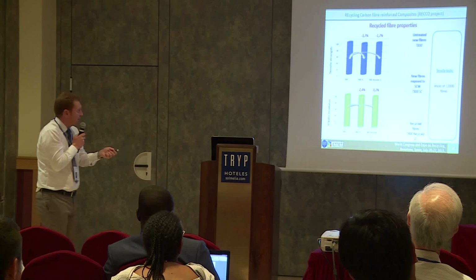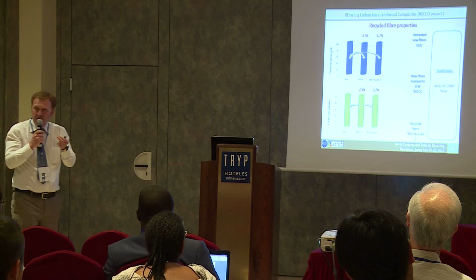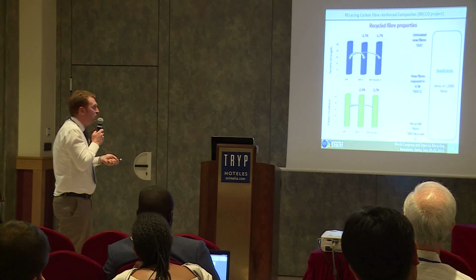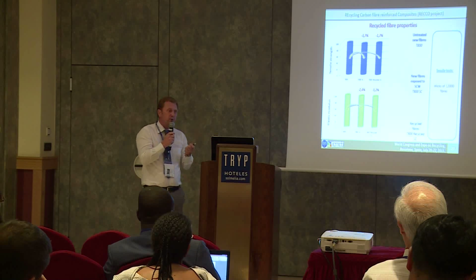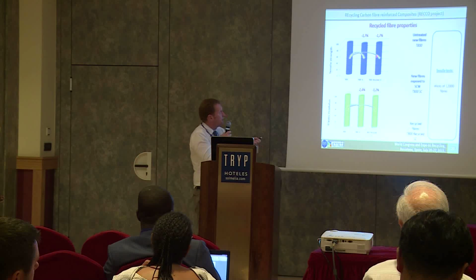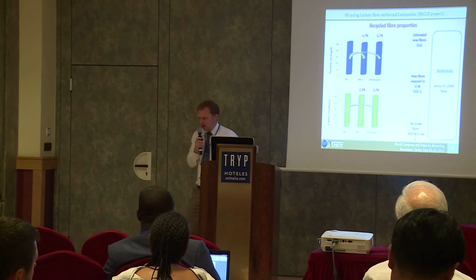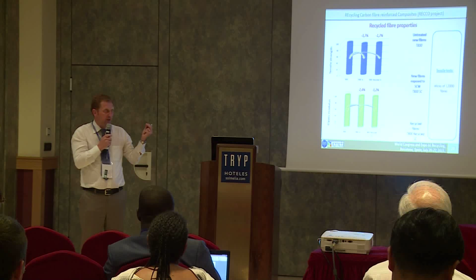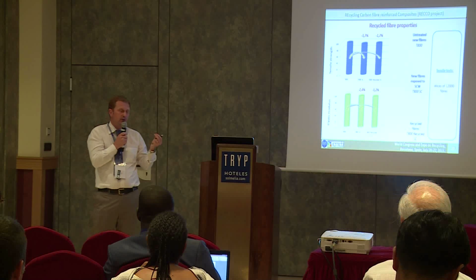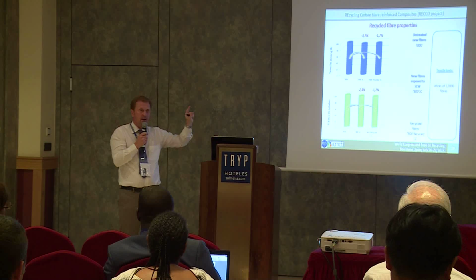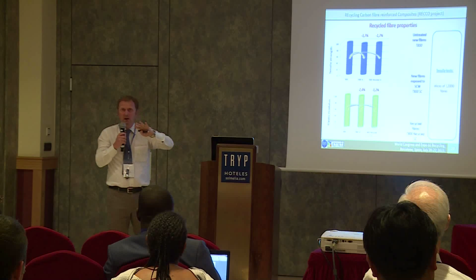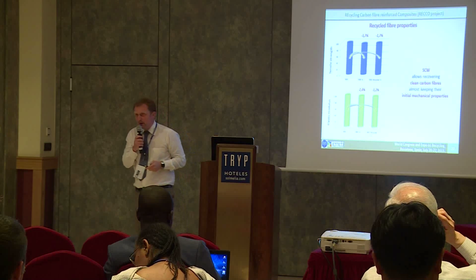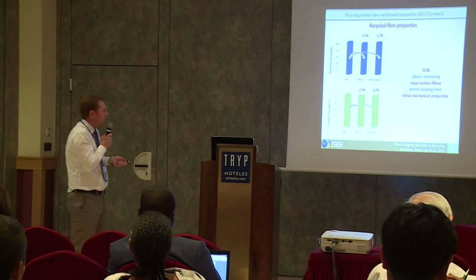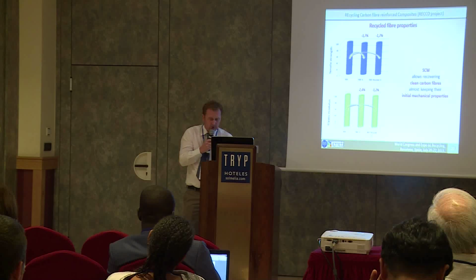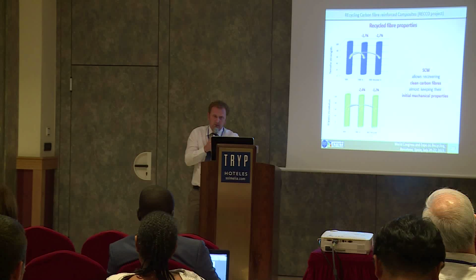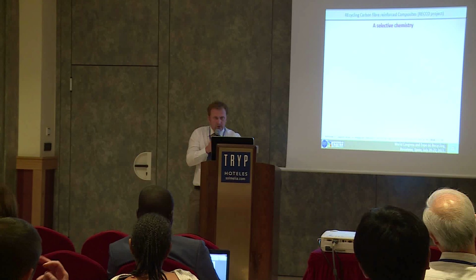What you can see is that there is not a strong impact of the treatment on the mechanical properties of the fiber. We are losing less than 5% of the mechanical properties of the initial material. It's between 1.7 and 4, knowing that it's difficult to compare this result with the untreated fiber, because the untreated fiber has the size at the surface, and the treated fibers are without this size. So this means we can consider that the supercritical fluid technology can really allow us to recover clean fiber, keeping almost the same initial mechanical properties. This is a very important result, and this has also been confirmed by other colleagues working on these topics.